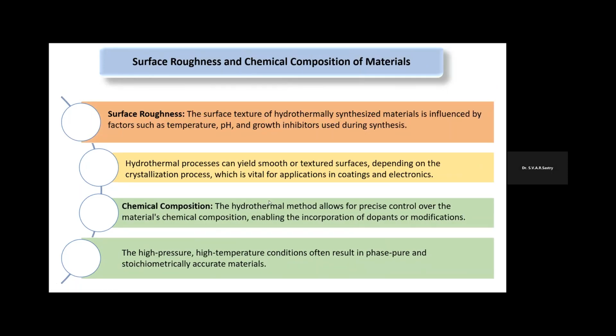Then coming to surface roughness and chemical composition of the materials, we see that the surface texture of the hydrothermally synthesized nanoparticles is influenced by factors like temperature, pH, and the growth inhibitors used during the synthesis. So the hydrothermal synthesis method can give a smooth or textured surface depending on the crystallization process, which is very, very important for the lubrication application especially.